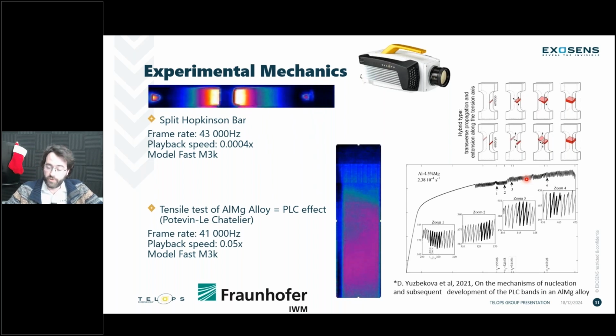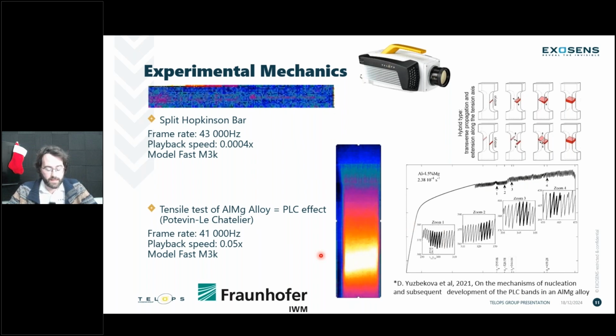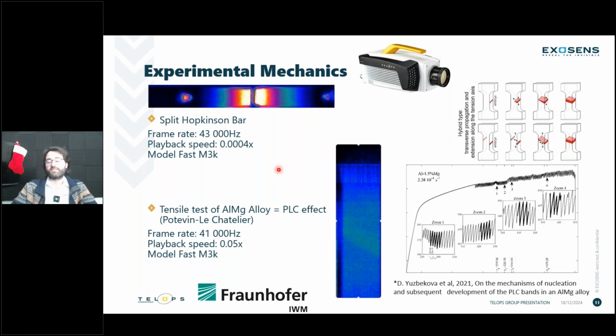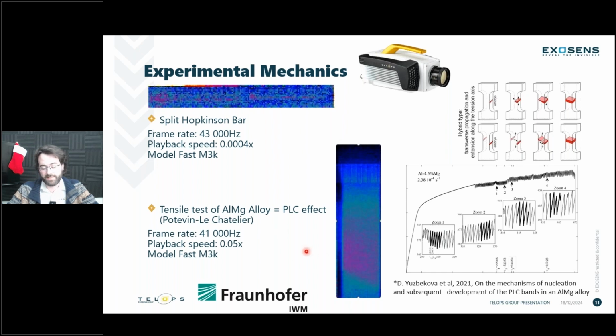Now, not a lot of people have been looking at this with infrared, but those dislocations that are creating weird stress strain behavior are visible because they're creating a heat release at those specific angles because of the dislocation. And so we can actually see those dislocations and that really fascinating phenomenon appearing in front of your eyes with the infrared imaging cameras. It's not a phenomenon that's as fast as the splitting or the compressing of the split Hopkinson bar, but it's a really interesting phenomenon, and people can actually understand the energy that's being released in that sort of beautiful phenomenon that we're observing here.